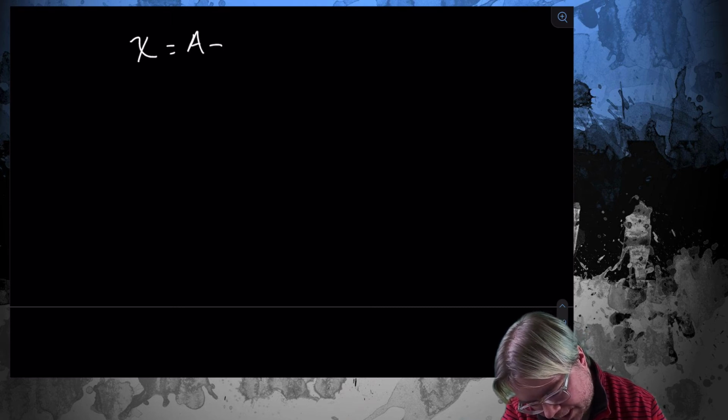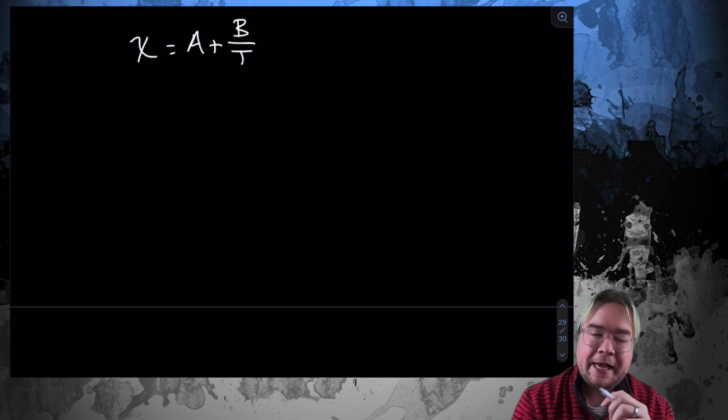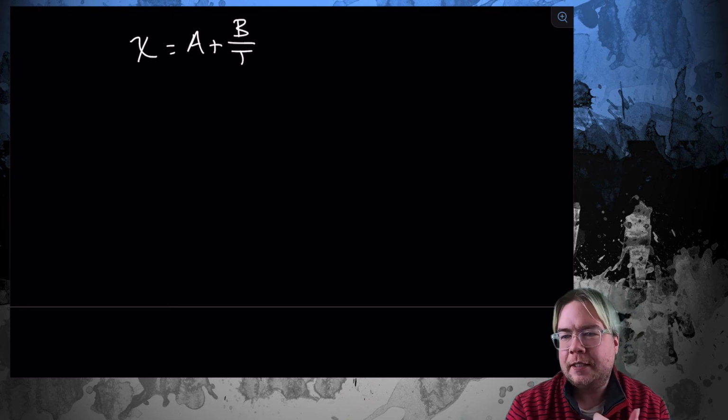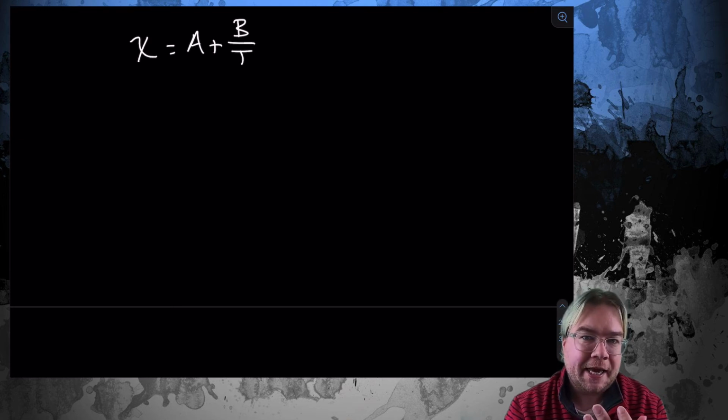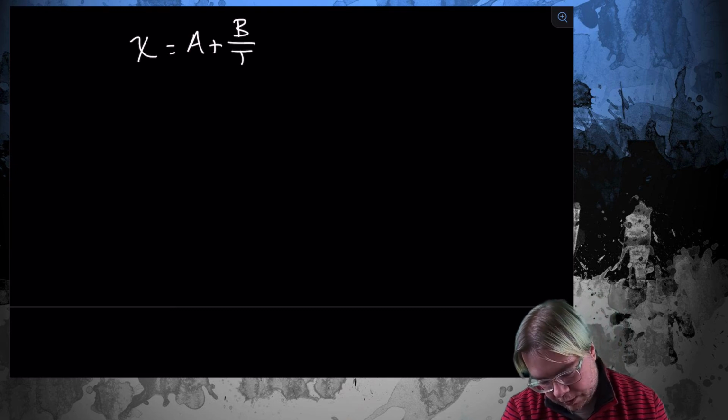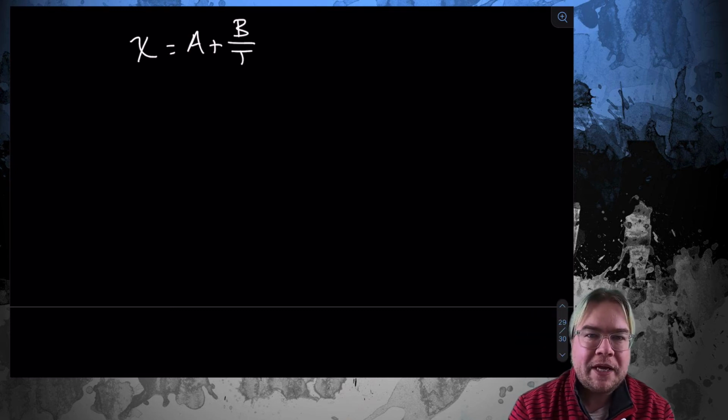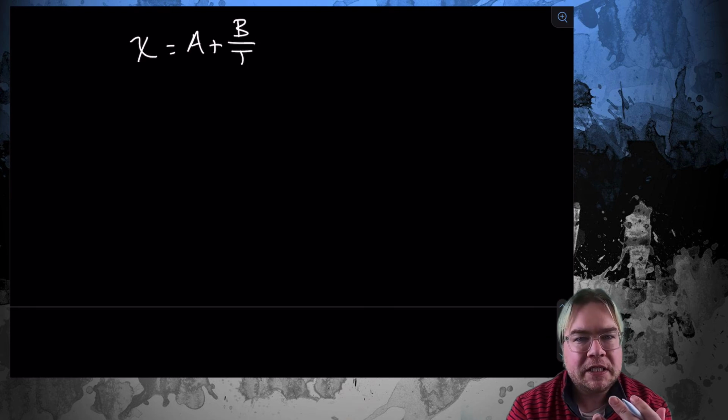Let's write down the Flory-Huggins parameter just in general. So remember, we can write it as A plus B over T, where once again, A is an entropic component to the Flory-Huggins parameter, and B over T is the energetic term. So B is really talking about energetics. So we could make A negative, we could make A 0, or we could make A very small.